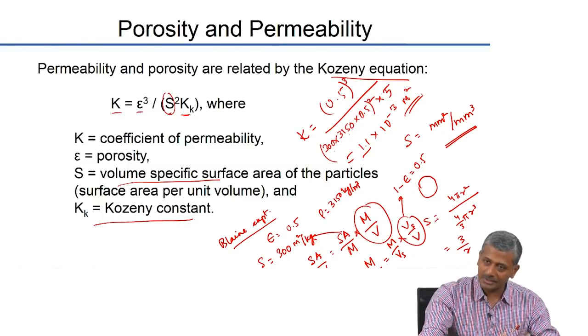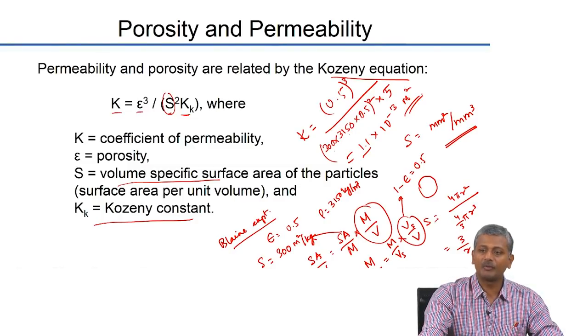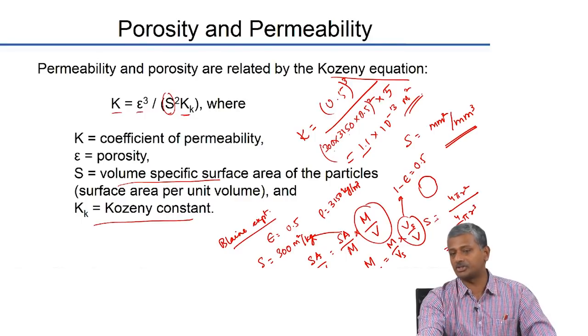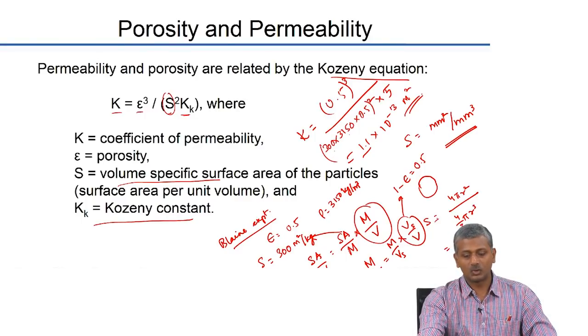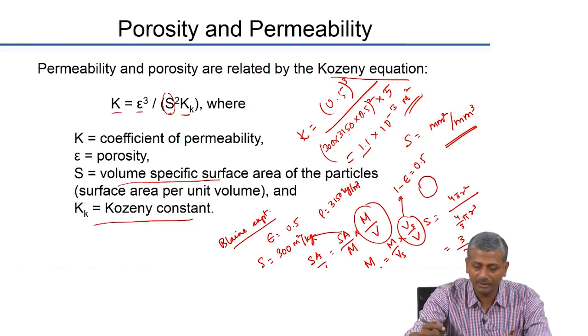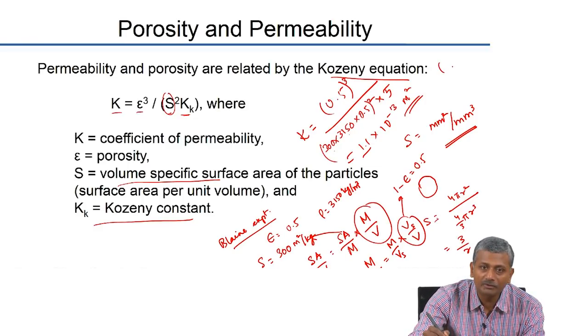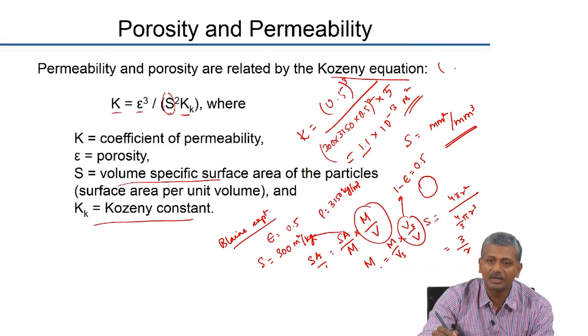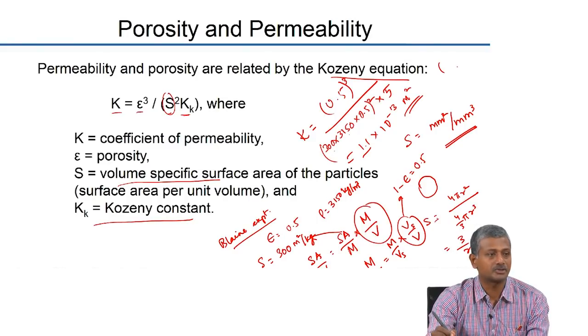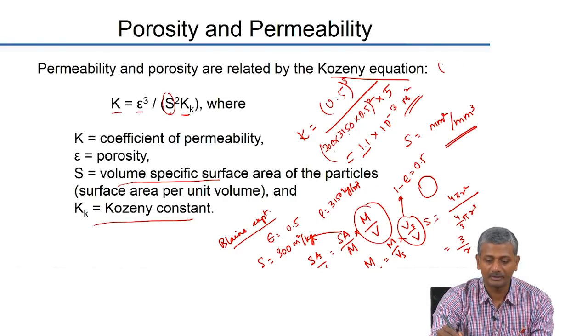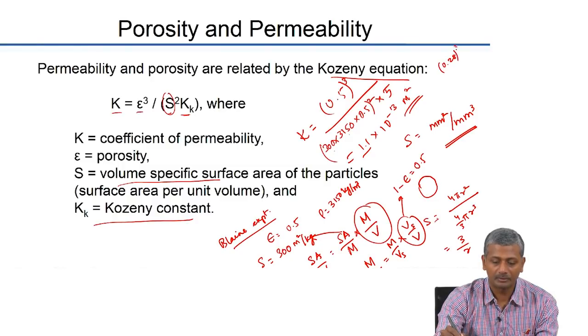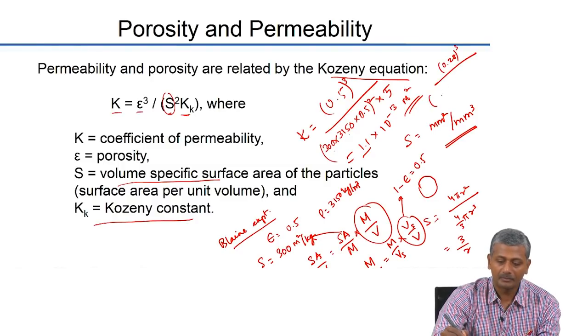Now, just in the same expression, if you were to work out the permeability of CSH, using the same expression, what values would you use for the porosity? What is the porosity of CSH? We assumed something when we calculated the hydrated cement paste structure, 28%, right? So 0.28 divided by what is the density, what is the surface area of CSH?